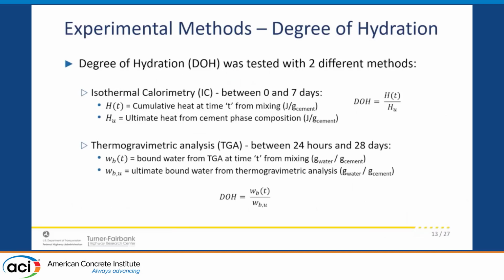One important factor we considered in our analysis was the degree of hydration of the system. Every admixture is going to have a slightly different effect on the development of the hydration products and the rate of hydration. Within the first 7 days, we relied on isothermal calorimetry, where we measured the cumulative heat and normalized it by the total reaction enthalpy, based on the chemical composition of the cement.